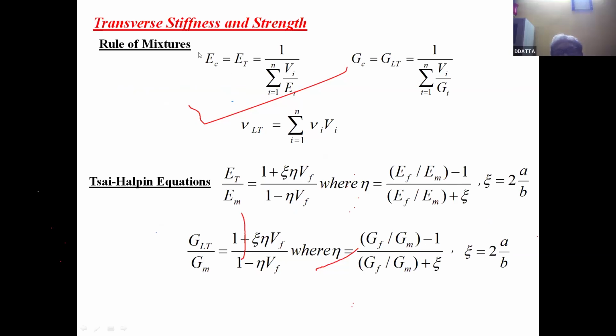So these are some of the rules of mixtures. One rule of mixtures I showed earlier, that E_L equals sigma E_i V_i. Now there are transverse properties also. Transverse means perpendicular to the fibers. So we call it the transverse direction, E_T, and this E_T will be this. Instead of a simple linear combination, it is a reciprocal combination, 1 by sigma V_i by E_i, and G_LT, the shear modulus, is also an inverse summation formula, 1 over sigma V_i by G_i.